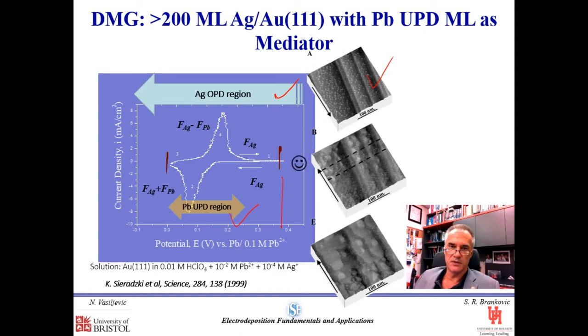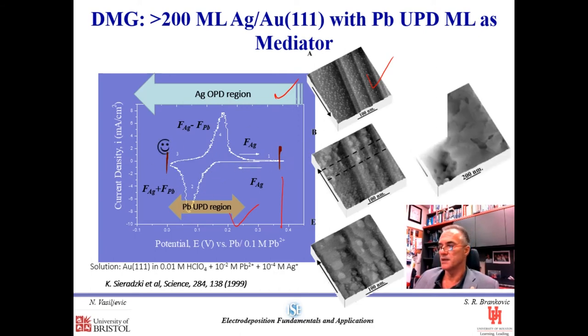If we keep continuing this over and over, we end up with a very high quality silver film on the gold surface. In this particular case, this is a silver single crystal film, on a single crystal gold surface.